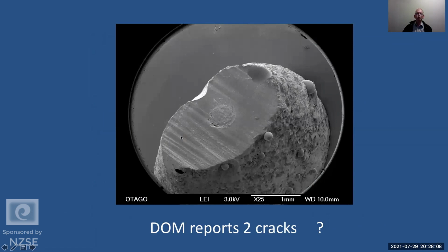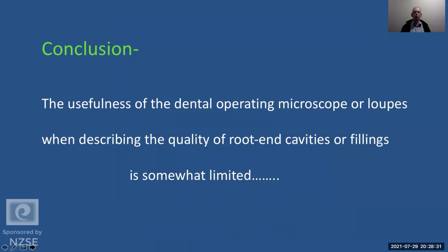With this particular tooth, and you can see it's got a kind of a dish-shaped bevel on it, the operating microscope reported 2 cracks. But I don't think there's any cracks there at all. There's a little bit of a deficiency. You can see the gutta percha and the sealer there. So there's a deficiency, but there certainly isn't a crack visible on that tooth. So our conclusion, and people didn't like it, was the usefulness of the operating microscope or loupes when looking at the quality of the root end cavity or filling was rather limited.